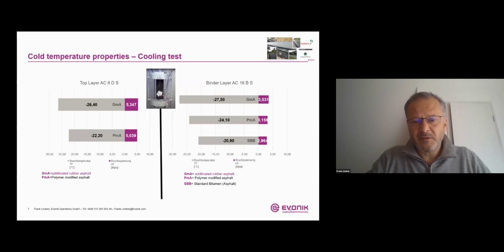What we see here for both the top layer on the left and the binder layer on the right is that superior performance comes with the use of rubber. And I have to say, again, we can see these results because this range of minus 26 to minus 27 degrees is what we typically see as a result in our cooling tests.